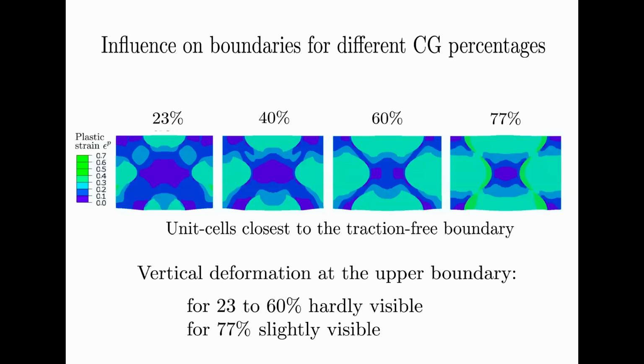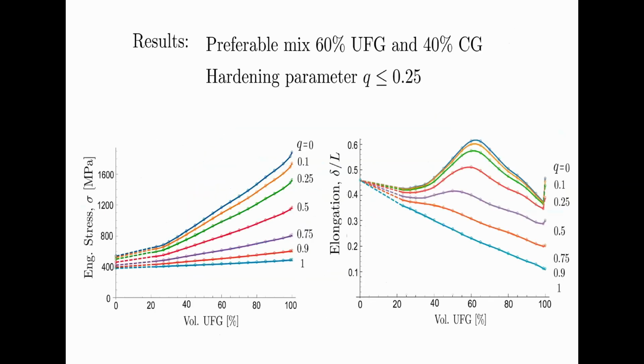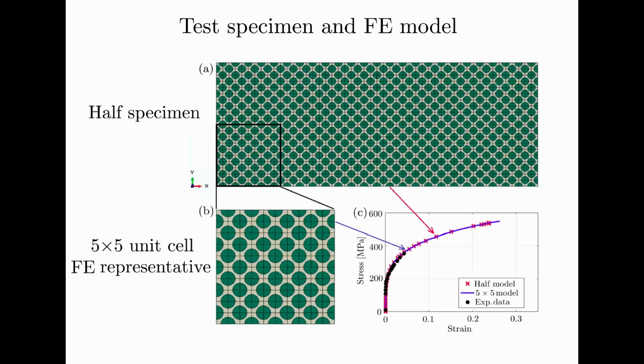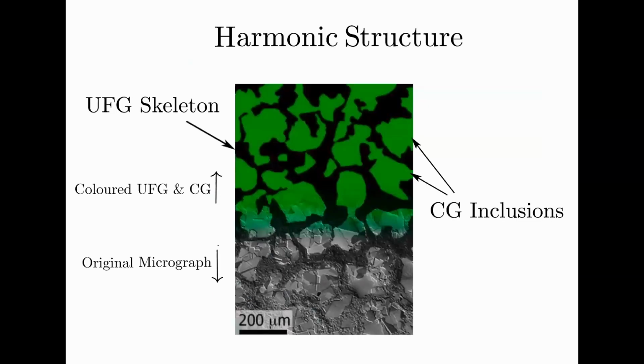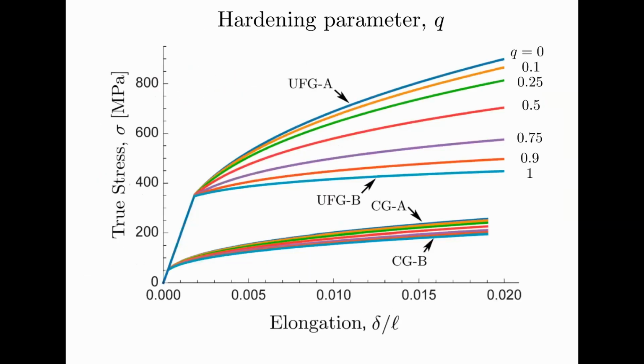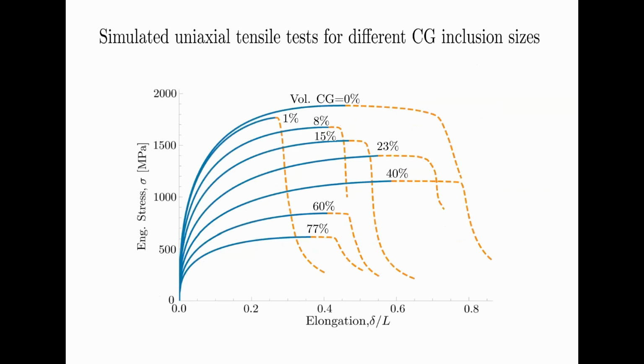But we would think that something would be happening up here. Here you see just little, and here perhaps, and here it's totally flat, which actually means that there is a symmetry line towards the second cell. Let me show you cells. So this cell row down here already is a symmetry line, which means that all of the others will be exactly the same, more or less. Only down here where it's traction free, you will have, which meant for us also that we could just as well have done this using 2 cells, one close to the boundary, and then all the rest will be the same.